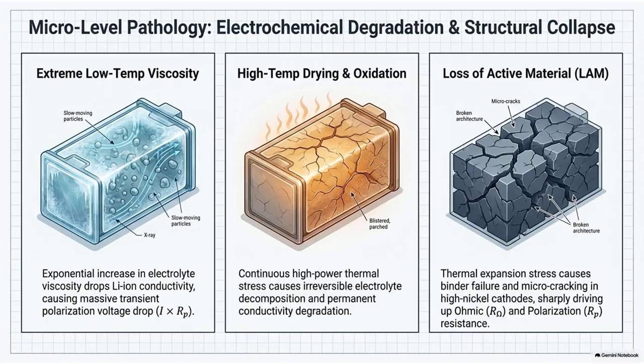Exactly. It's microscopic, obviously, but it is a violent physical volume expansion and contraction at the atomic level. Okay, I can see where this is going. Now, combine that constant mechanical flexing with massive thermal stress from high-power driving. Over time, the structural binders like PVDF that hold the electrode particles to the conductive current collectors begin to fail. The glue gives out. Yeah, the active material literally cracks and detaches from the conductive framework.